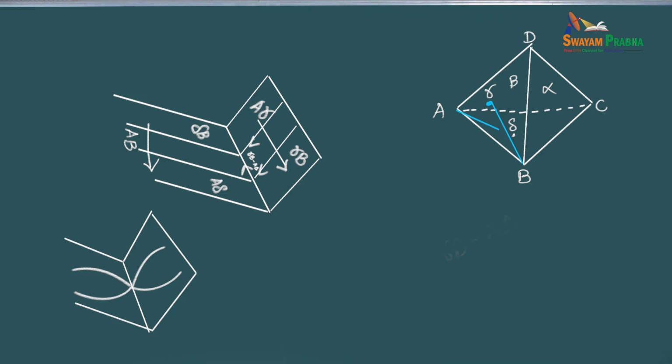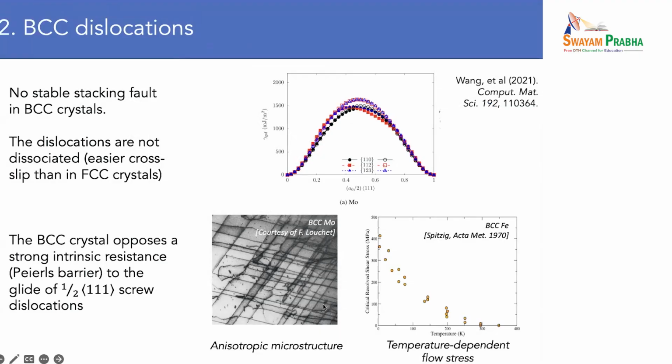Yes, sure. The equilibrium, so if there was no line tension, the segment here, because it's big, it would be completely zero. But to be completely zero, you have a large price to pay. And so there's an equilibrium between the line tension of the dislocations there. So it's not necessarily exactly zero. It would be much smaller than the other one, but it will not be exactly zero.